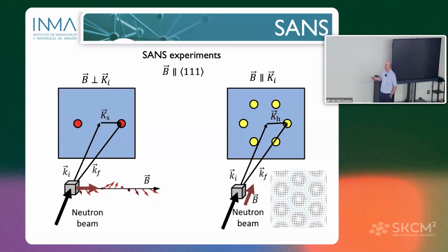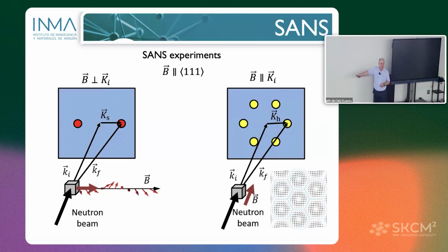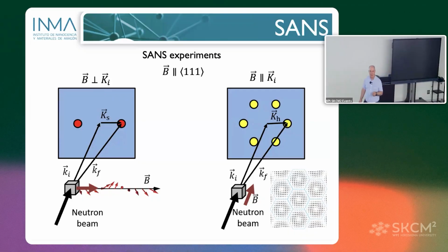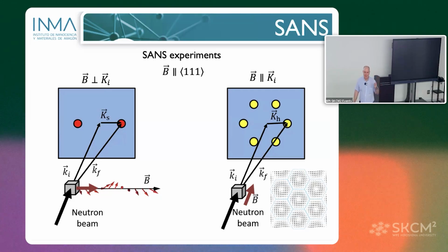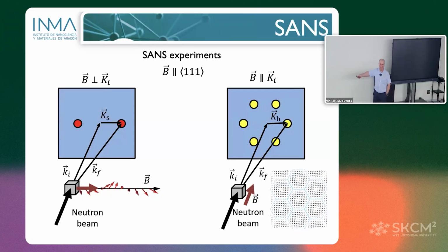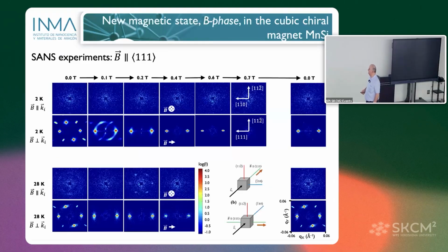With this configuration, you will have 6 points because the lattice is hexagonal, but if you have a square skyrmion lattice, you will find only 4 points. This number of points depends on the symmetry of your lattice, okay? And these are typically the 2 configurations that we use to describe and to find the skyrmions with SANS.